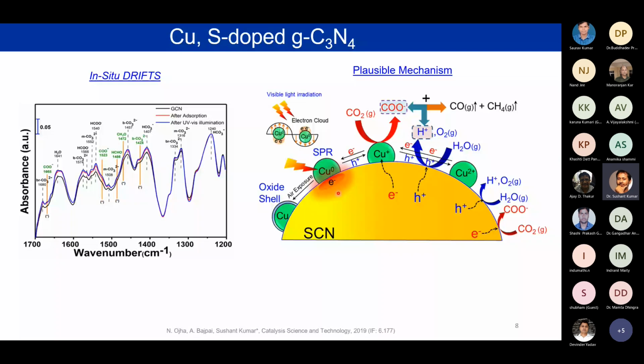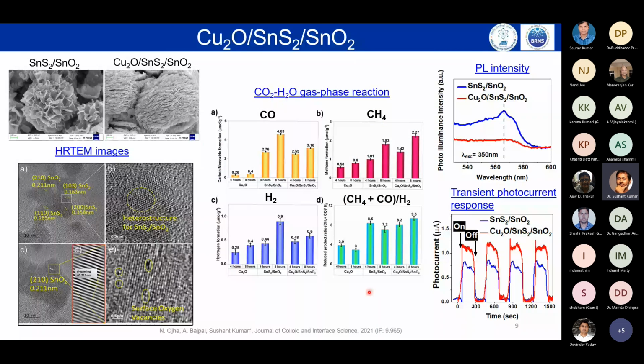And then what we did in a different work is we were excited in knowing what will be the effect when we have a PN heterojunction, because we know that we have to somehow separate these electrons and holes so that the recombination would not happen and we can get more electrons on the surface. And to do that, we should be able to control or tailor the photocatalyst in a way that it should not recombine too much. So to do that, we have used the Cu2O, and first we have prepared the SnS2 and SnO2. The reason why we use this SnO2 and SnS2 is that they have a lot of oxygen vacancies, which I will show you.